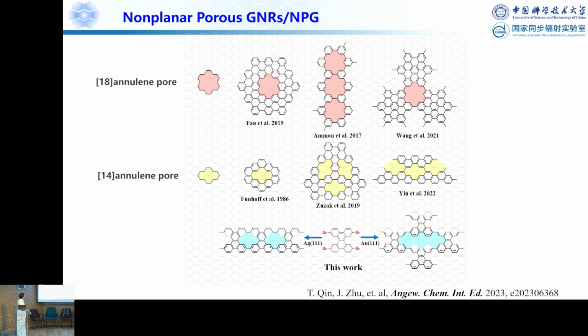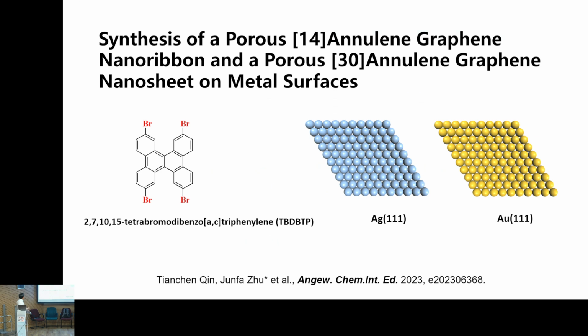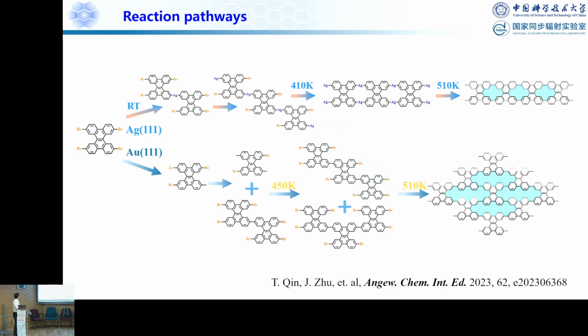Okay. So the next sample I want to show, we embedded the pores into the graphene nanoribbons. First, in the literature you can see a lot of these examples, which I don't have to show here. We use these precursor molecules and different substrates, silver 111 and gold 111, and the reaction scheme is like this. On silver 111, you can see we finally form graphene nanoribbons with 14-annulene pores.